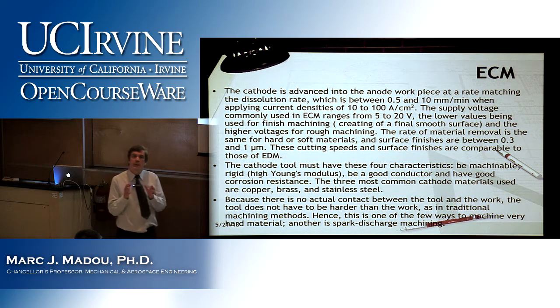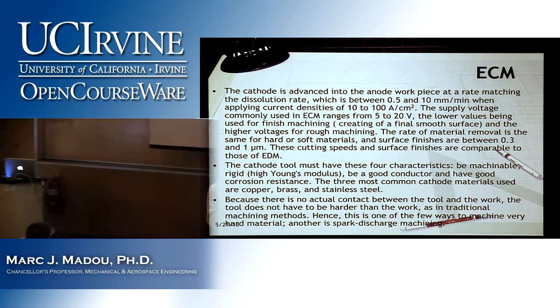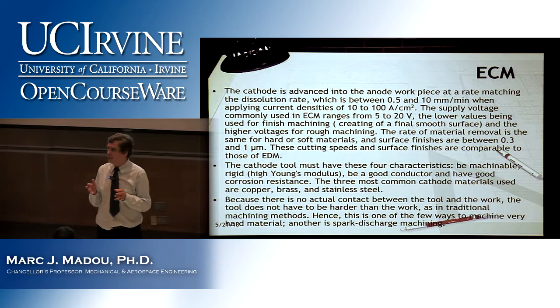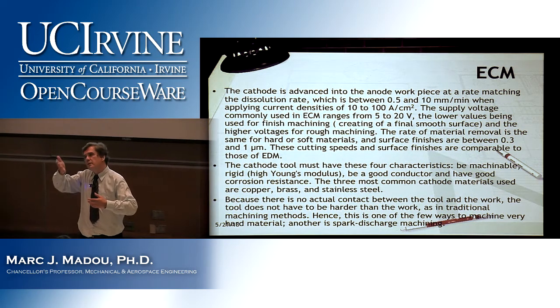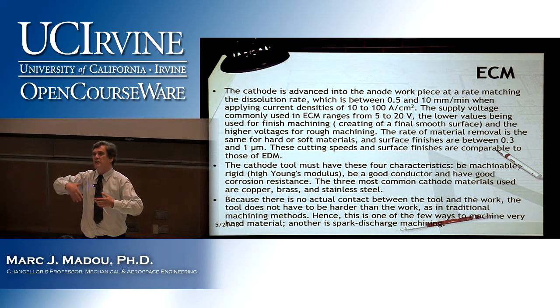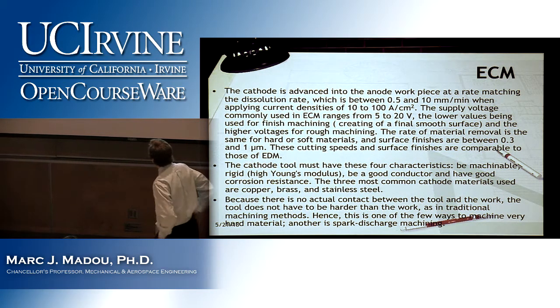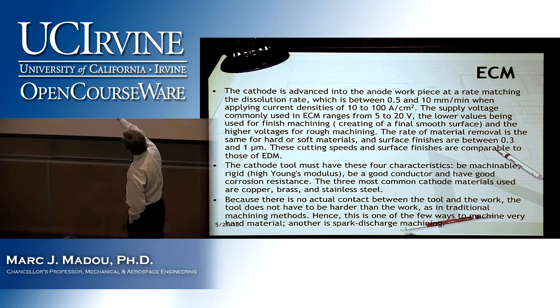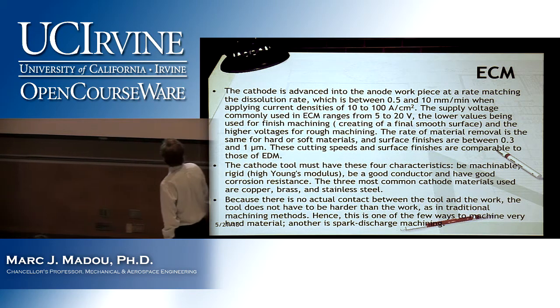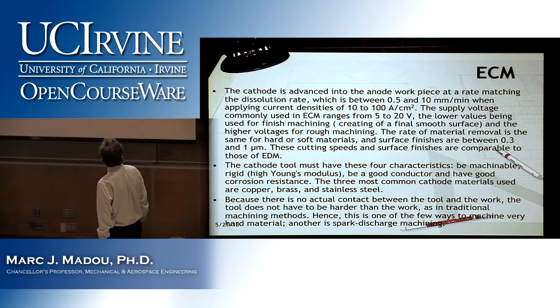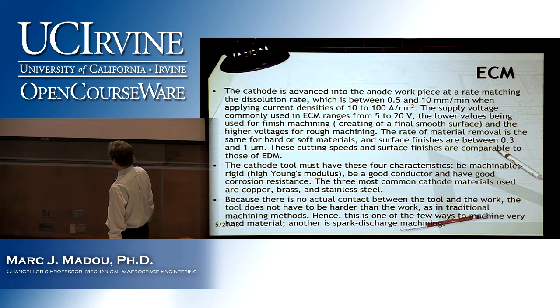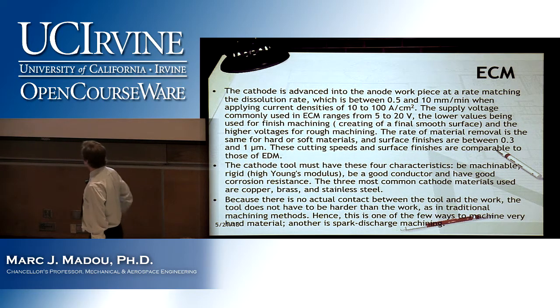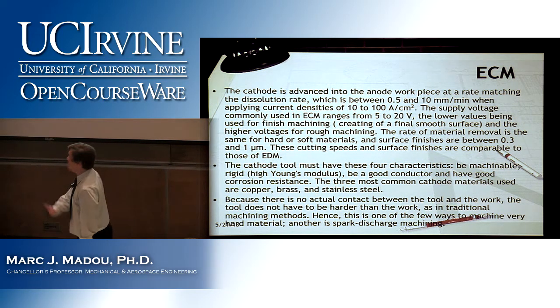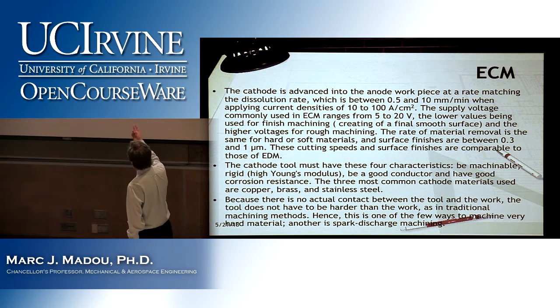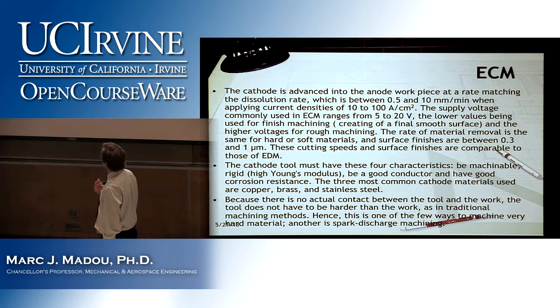Well, that's another tool. The roughness of the part will actually depend on the size of the current. So if you have higher current, your workpiece will be carved out with rougher edges. Then reducing the current, you will have smoother surfaces. So actually, the cutting speeds and surface finishes are somewhat comparable to those of EDM. And the rate of material removal is the same for hard and soft materials. We already guessed that, right? And surface finishes can be as good as 0.3 to 1 micron.